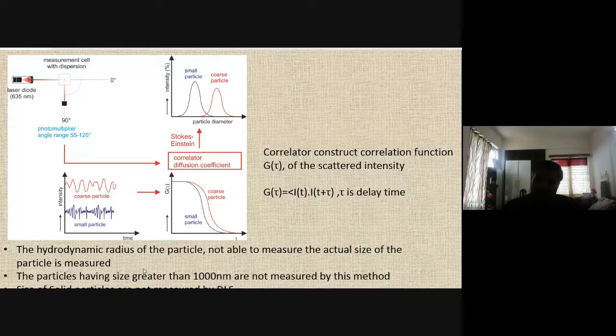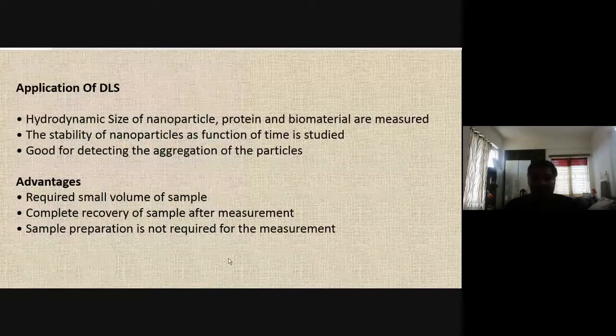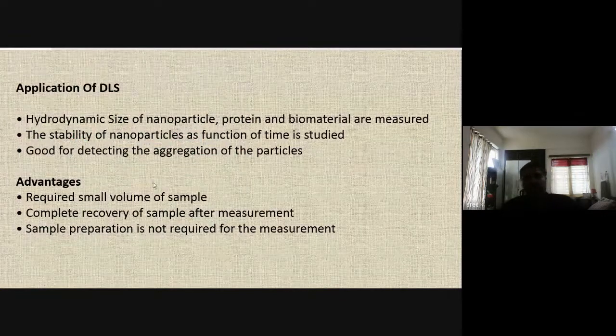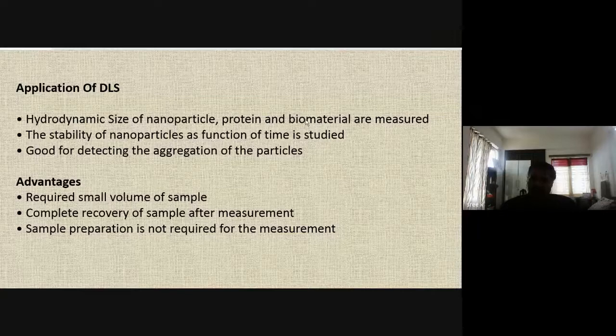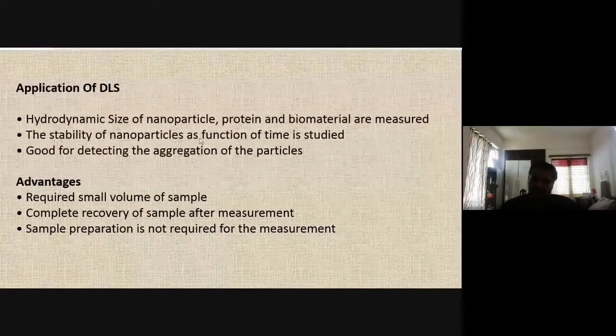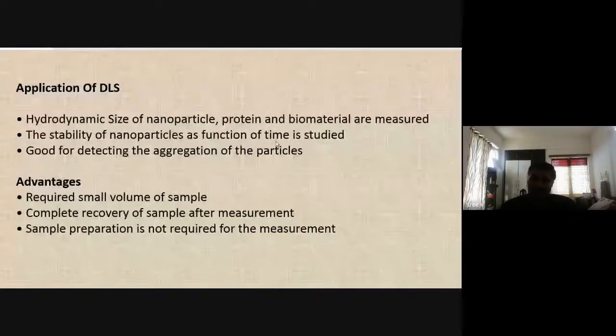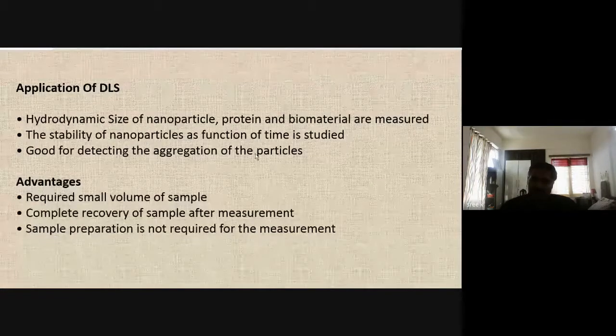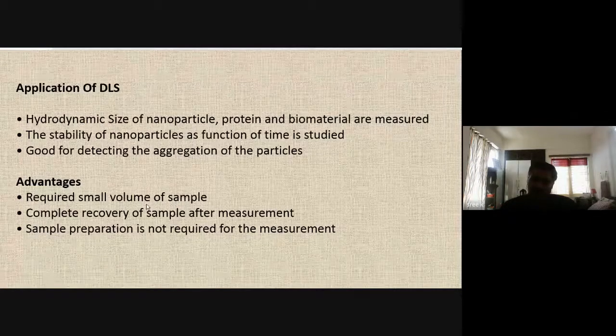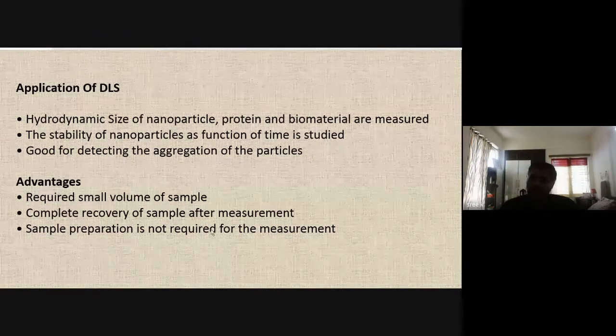Particles having a size greater than 1000 nanometers are not measured by this method. Size of solid particles are also not measured by DLS. Applications include measuring hydrodynamic size of nanoparticles, proteins, and biomaterials, studying the stability of nanoparticles as a function of time, and detecting aggregation of particles. It requires only a small sample volume, allows complete recovery of sample after measurement, and sample preparation is not required.